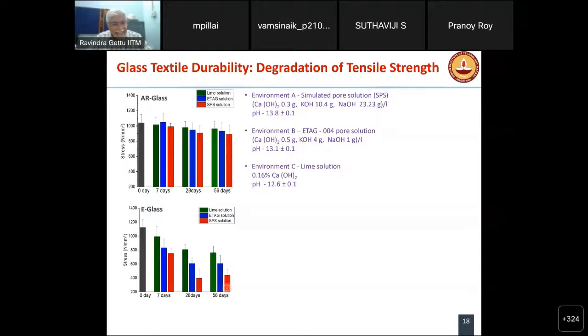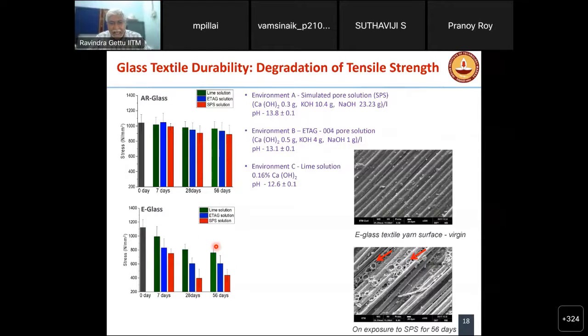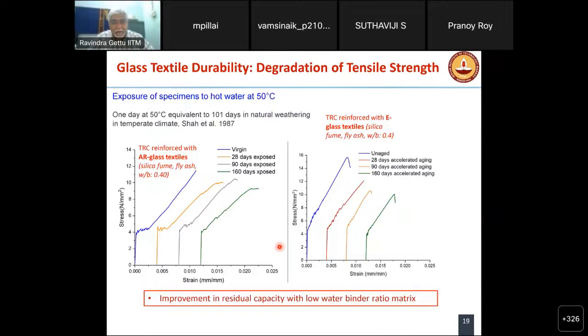However, when we have E-glass, which is a cheaper glass, a more common glass, we find that strength loss is occurring. And if you look at it carefully, you see that the E-glass, instead of being like this, like in the top image, starts to have pitting. And there is something like corrosion which is occurring where the glass is degrading. This is what we want to prevent. We want to use E-glass as much as possible because it's a cheaper glass, it's a more common glass, but we also want to make it more efficient. So this is what we are working on.